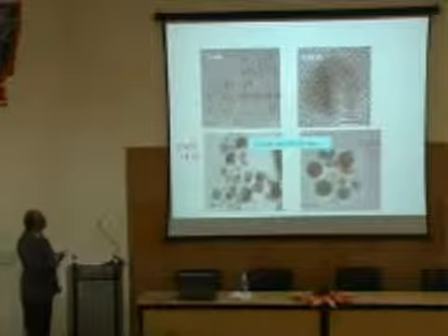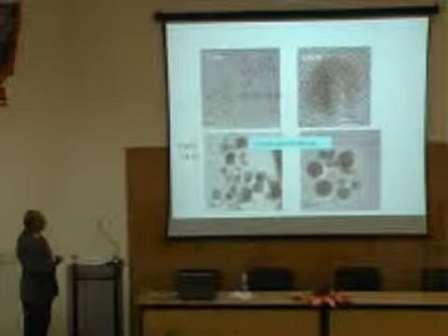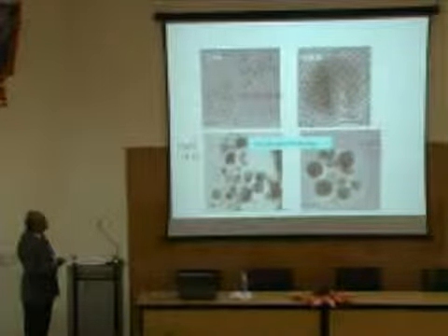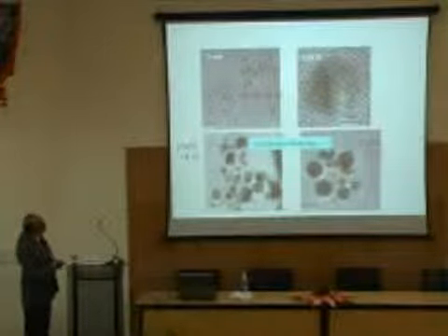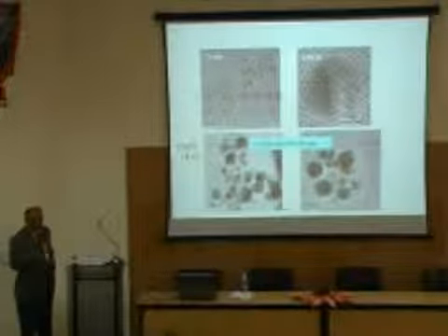This is another aspect, nanometals or nanoalloys, with a similar process of synthesis using microemulsions, and I will not bore you. These are the type of nanoparticles you get. You can get pure copper, you can get pure nickel, you can vary the ratio 1:3. This is a high resolution picture to show that the particles are very, very small. Maybe this is 2 nanometers. So, this particle may be around 5 nanometer dimension. Okay. And you can vary the composition easily, and by varying the copper nickel ratio, you can vary the properties of these materials. Okay.